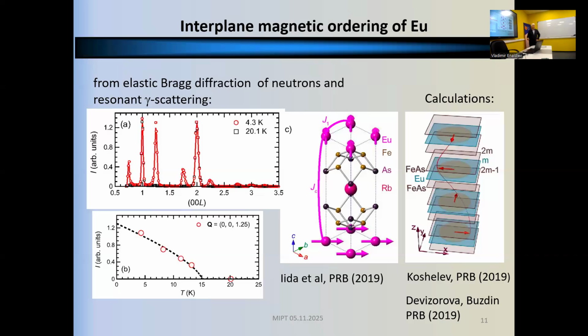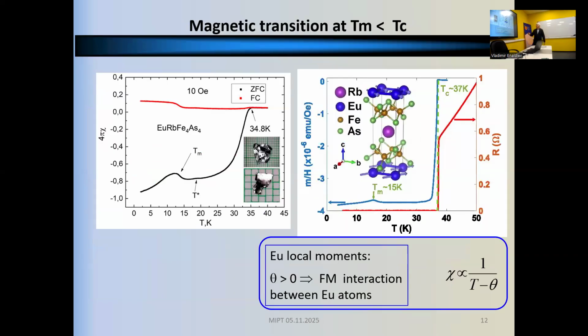So something should occur at 15 Kelvin, and this was immediately seen in experiment. When you study, say, AC susceptibility, you see some hump around this magnetic temperature. So definitely there is some weak effect of magnetic ordering. Of course, nothing can be seen in transport, on the drop of the resistance, and even on M over H, this is a DC magnetization, there could be something noticed in the vicinity of the magnetic ordering. But actually, we were puzzled because we expected that